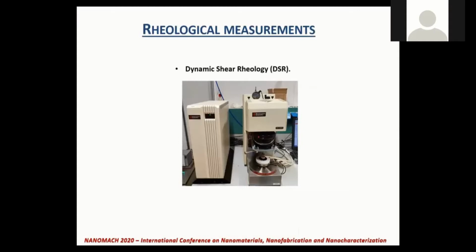Rheological measurements. To evaluate the effectiveness of rejuvenating agents, the rheological measurements were performed before and after the aging process, with or without additive. In general, after the aging process, the viscosity property changes and the transition temperature increases. A good additive restores the aged bitumen to values similar to the pristine bitumen before the aging process. To determine the rheological property and the transition temperature, rheological measurement has been done.